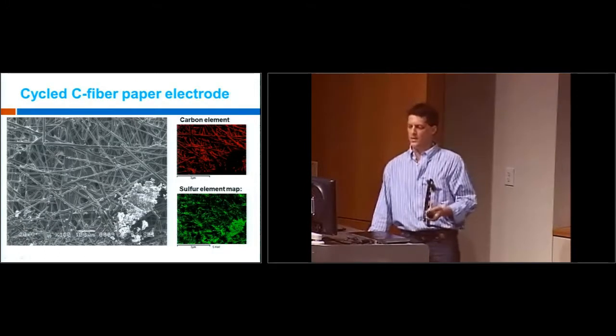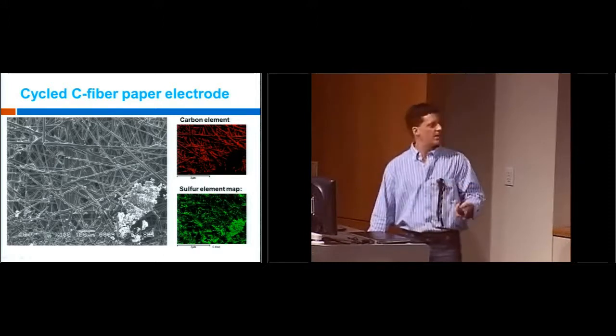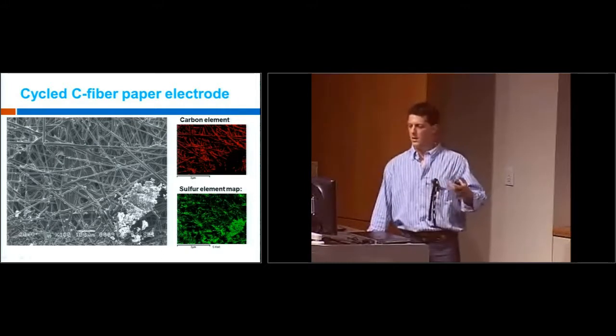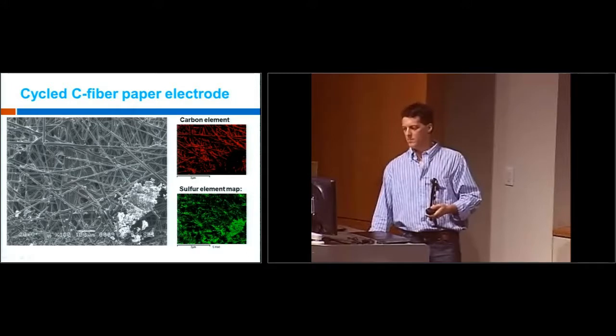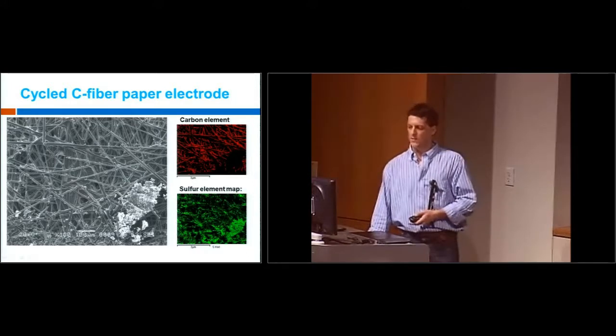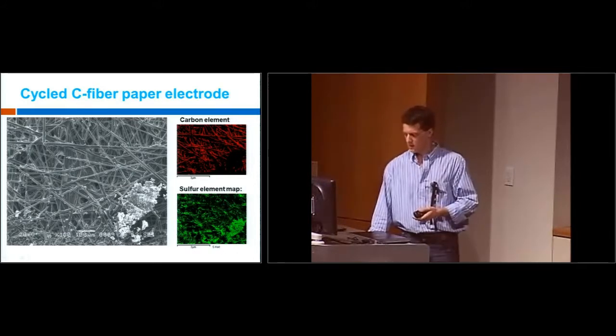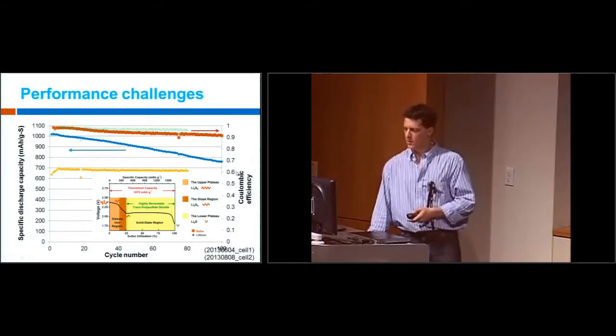So what basically happens is the active material becomes liquid, and then it is sort of sequestered away from the electrode and precipitates during discharge and is no longer accessible. Physically, you can see this is all sulfur. Here is the carbon, and you can see the sulfur is completely detached. It's no longer in contact with the carbon.